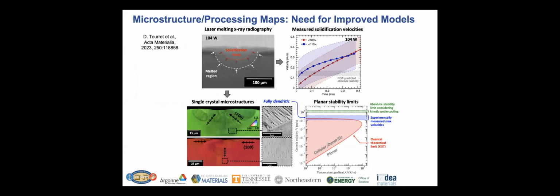So going back to these microstructure processing maps, we know we need some improved models. So looking back at an example spot melt, where again, we can track the solidification velocity. Here we have velocity versus time for a low power, well-behaved melt pool, and different velocities for different crystal orientations that we looked at. We can go and do the post-mortem characterization as shown here.